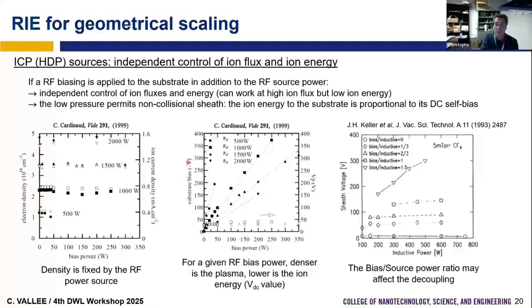So the value of the DC self-bias you will extract of the ion energy will depend on the source power. Usually, the denser the plasma, the lower the self-bias voltage. Because if you apply a bias power, the power is a product between the voltage and the current. So when the plasma is dense, you have a lot of current going to the substrate, so you need to develop less voltage. So at the end, the DC self-bias is less compared to the DC self-bias with 500 watt.